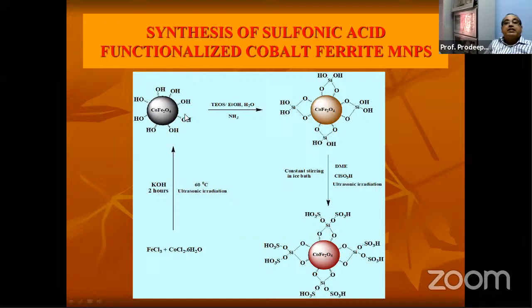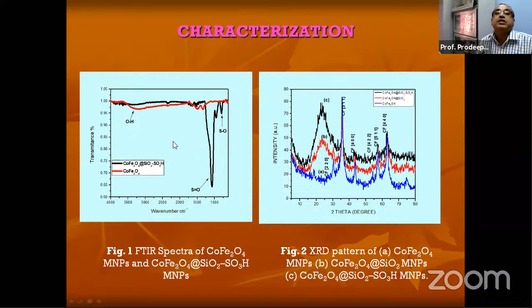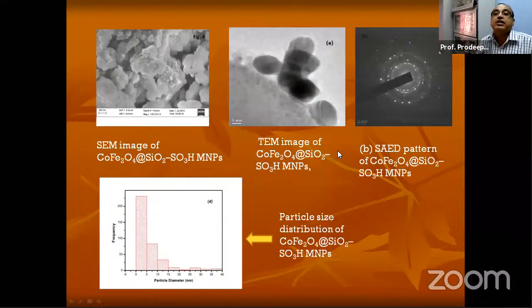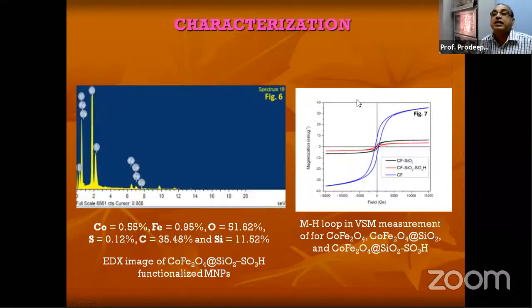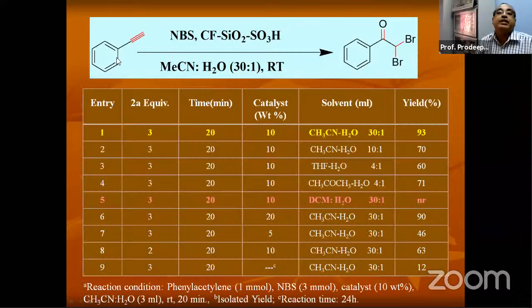First, we made this catalyst, magnetic nanoparticle. Then we have done this surface coating. Then still OH is there. Then chlorosulfonic acid we have used, with ultrasonic irradiation. Then this acid property has been introduced on the surface of the nanoparticle. So these are characterizations. I will not talk about details. And finally, we have used this for oxidative bromination.